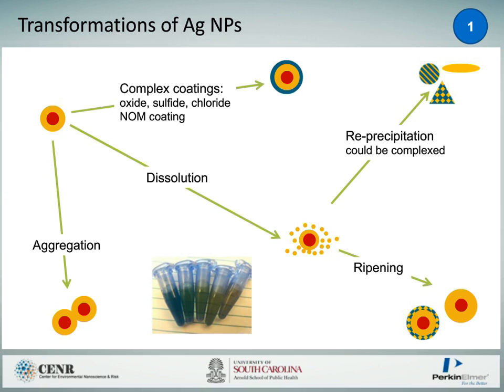from the dissolved material. The photograph at the bottom of this slide just shows silver nanoparticles that have been exposed to different conditions, and you can see they've gone from their usual yellow color to a rainbow effect. So we have some blue, green, and even red colored nanoparticles.